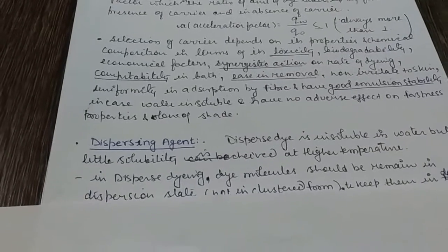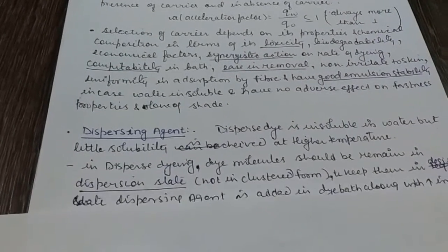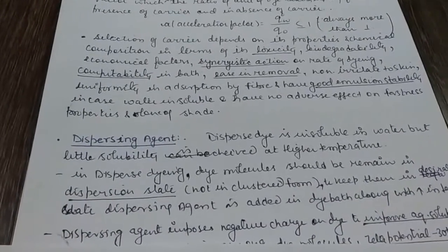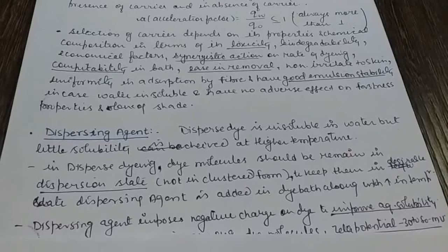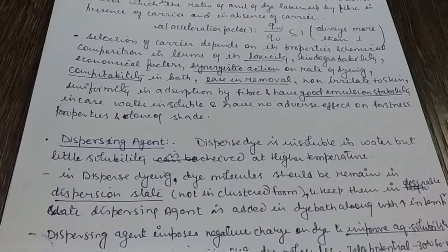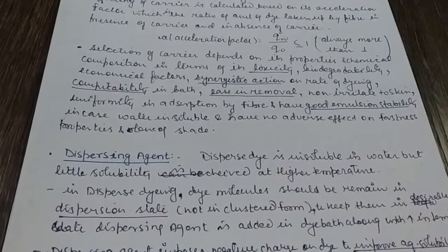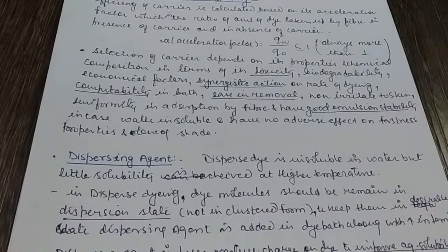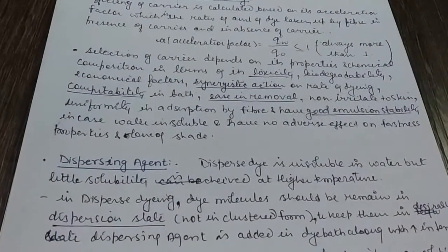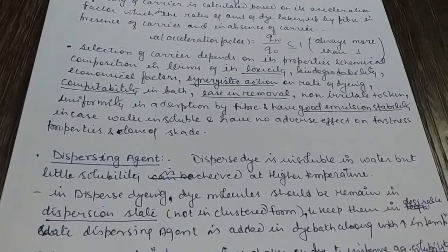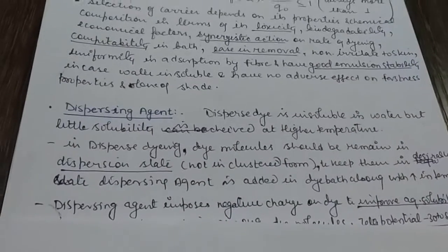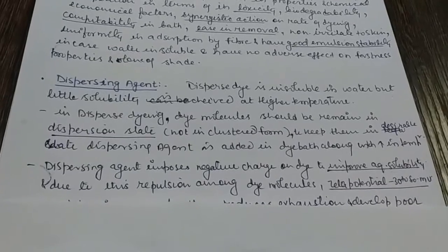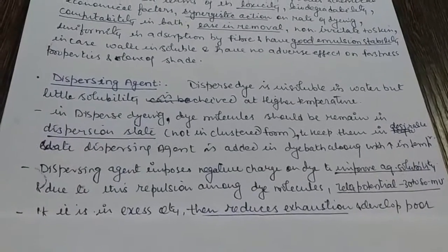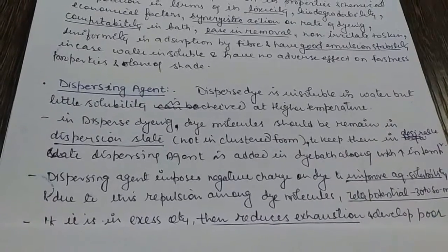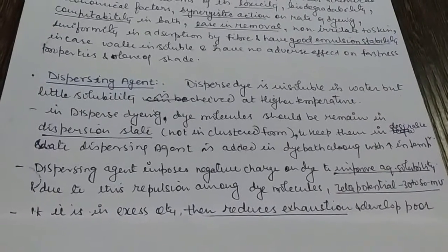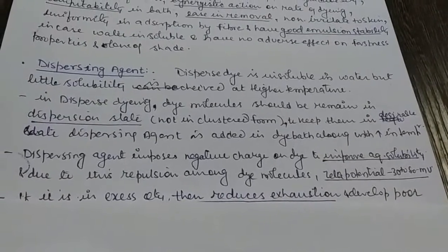In dispersed dyeing, dye molecules should be remain in dispersion state, not in clustered form. To keep them in desired state, dispersing agent is added in dye bath along with increasing in temperature. So when we add dispersing agent in dye bath, then solubility of dispersed dye is increased, but simultaneously by increasing the temperature of dye bath, also solubility increased. Dispersing agent impose negative charge on dye to improve aqueous solubility, and due to this, repulsion among dye molecules increase, means zeta potential is minus 30 mV to 50 mV.